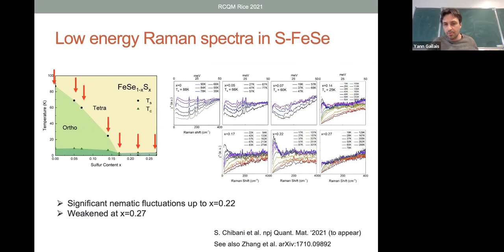And if you dope further, so you enter compositions at which no structural transition is seen, essentially the spectra show the development of this quasi-elastic peak down to the lowest temperature. Note that at the highest concentration, so 27%, this enhancement is significantly reduced. So there is already a signal at this sulfur composition that the nematic fluctuations start to decrease significantly.